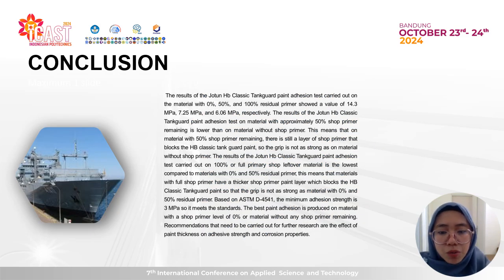And the conclusion of this research is that the results of the Jotun HB Classic Tankguard paint adhesion test carried out on the material with 0%, 50%, and 100% residual primer have values of 14.3, 7.25, and 6.06 MPa respectively. The result of the adhesion test on material with approximately 50% shop primer remaining is lower than on material without shop primer. This means that on material with 50% shop primer remaining, there is still a layer of shop primer that blocks the HB Classic Tankguard paint, so the grip is not as strong as on material without shop primer.